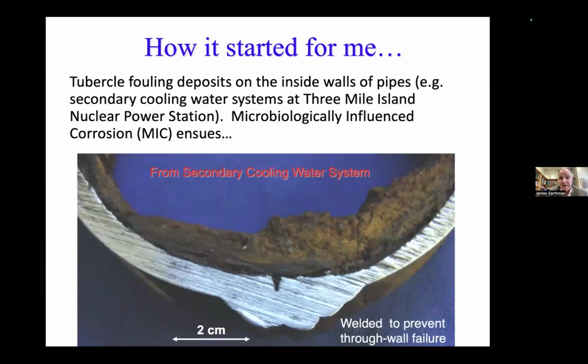Here's another pipe that had this problem. The localized corrosion was going down a weld seam, the one weld seam that the pipe had. Bacteria are very efficient. They always colonize where they can get the fastest corrosion going, the most iron sulfide producing. And at the weld seam, it's weaker there, so that was a susceptible region for localized corrosion. And they were just going down that weld seam.